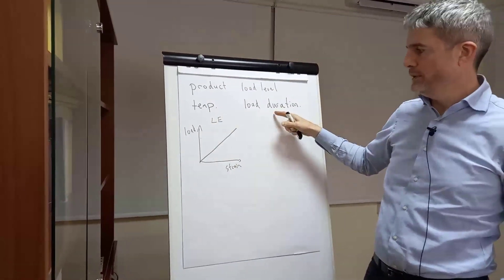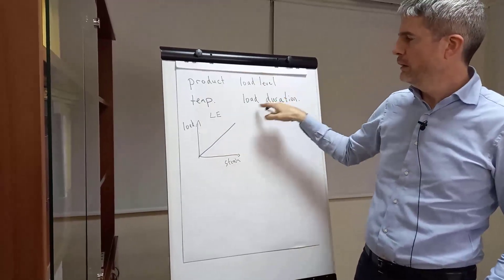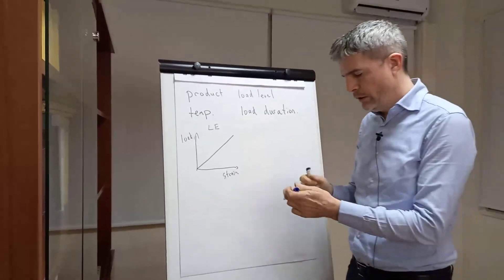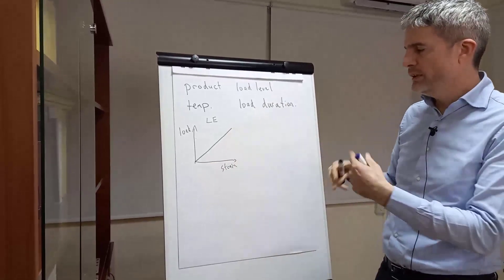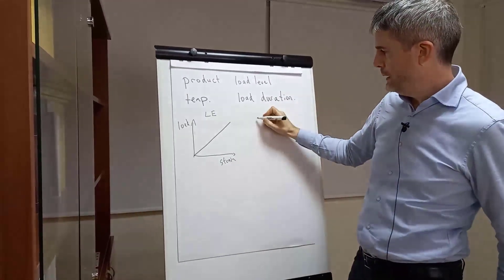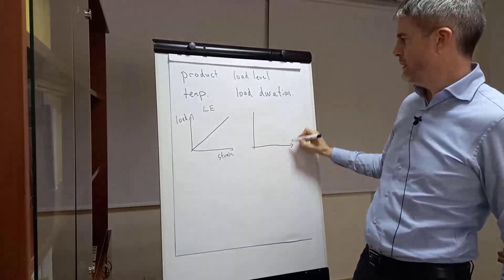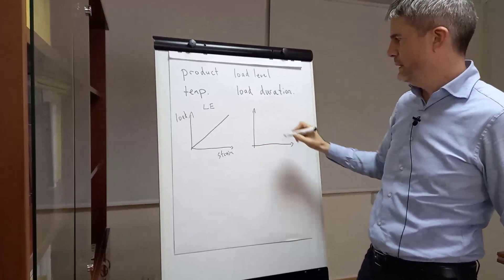So we take the average properties from stiffness testing on larger samples of the geogrid. We never break it down to individual E and A values - it's just expressed as an overall average EA. When you're doing a linear elastic model, you need to choose one EA value that takes into account the product characteristics, the load level, the temperature, and the load duration. So it's actually quite difficult to find one value that's going to be correct for all of those.